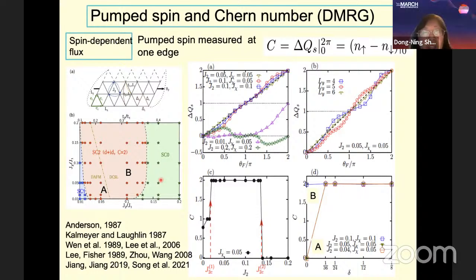Yeah, there are different possibilities for inducing this term. One is that if we have a magnetic field, then when you expand the Hubbard model to the TJ model, there's a three-spin interaction. Another possibility is that for some Hubbard models, if we start from a twisted TMD system, then the electron hopping itself will carry a phase, which can also result in the chiral interaction. But our motivation is to try to figure out if we start from half filling with the chiral spin liquid, what kind of superconductivity we can obtain.